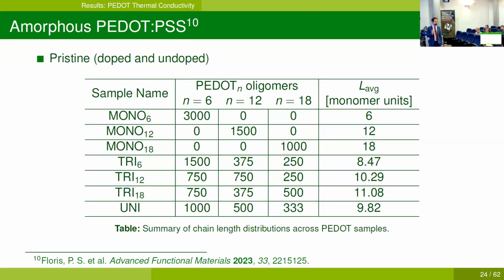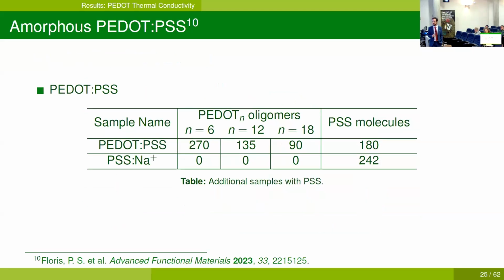Sorry, one more thing. The doped PEDOT samples, of course, bear a positive charge, and it needs to be counterbalanced by chlorine anions to preserve charge neutrality in the box. There is only one PEDOT:PSS sample with this chain length distribution and 180 PSS molecules. And we have also created a sample which only contains PSS with its negative charge balanced by sodium cations with no PEDOT, so 0, 0, 0.